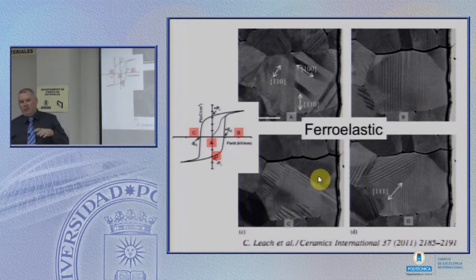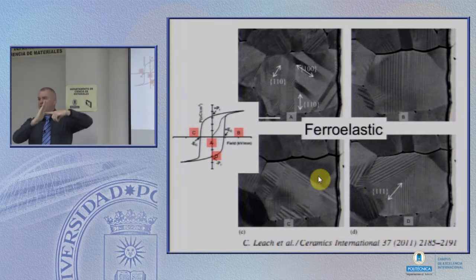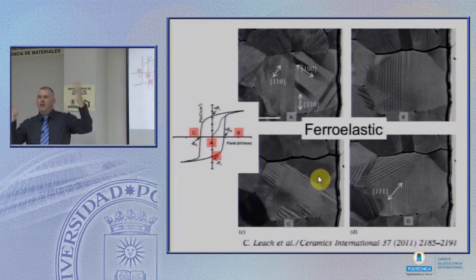Because of that possibility, these materials at a high temperature typically are cubic. As we cool them through the Curie temperature, the individual crystals, usually because of the interactions with the grains around them, don't just become tetragonal from one orientation, they pick multiple orientations. And then you end up with the possibility of this and this coming up against one another. These are two domains, and the boundary between those is a domain boundary, right? And usually when we process the material, for every crystal we end up with about equal fractions of this, this, and this.